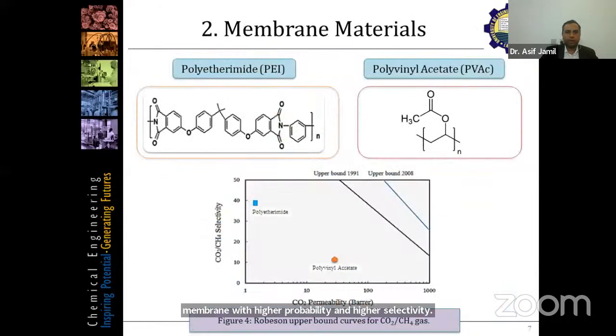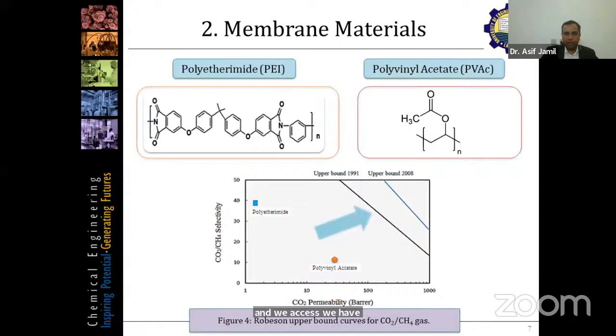For that, specifically, we choose polyetherimide, and the rubbery polymer is polyvinyl acetate. If we look at the graph here, which is the Robeson upper bound curve, this is what is desired. We want our polymers to reach as close as possible to this curve. Polyetherimide has very high selectivity; on the y-axis we have CO2/CH4 selectivity. Polyvinyl acetate has much lower selectivity, but its permeability is higher compared to polyetherimide. That's why we choose these two polymers.